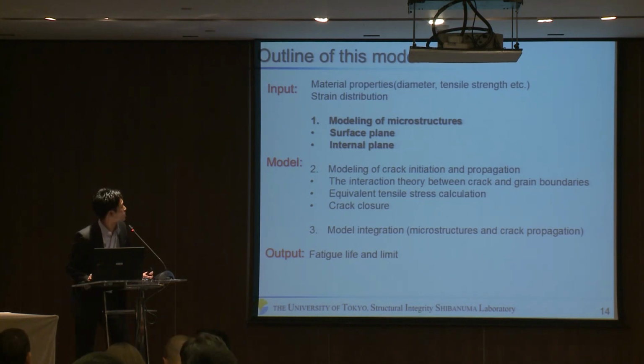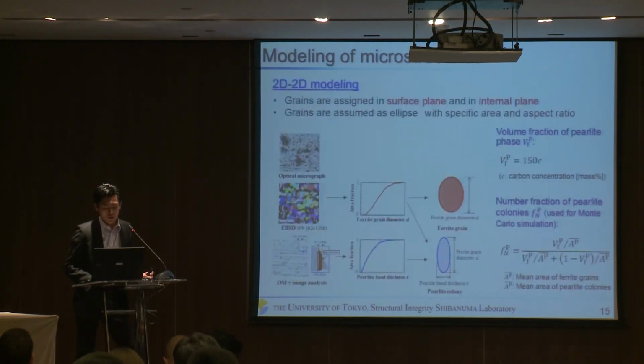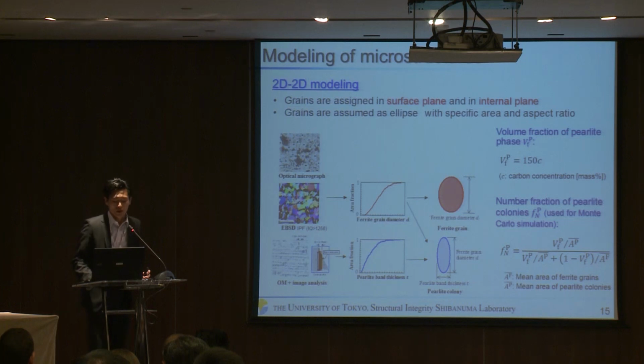Next, modeling of microstructures. In this model, three-dimensional fracture phenomenon is assumed as a two-dimensional phenomenon: the surface plane and internal plane. Microstructures are modeled by randomly assigning grains in the surface plane and internal plane. And to simplify the assigning procedure, grains are assumed as ellipses with a specific area, aspect ratio and grain orientation.